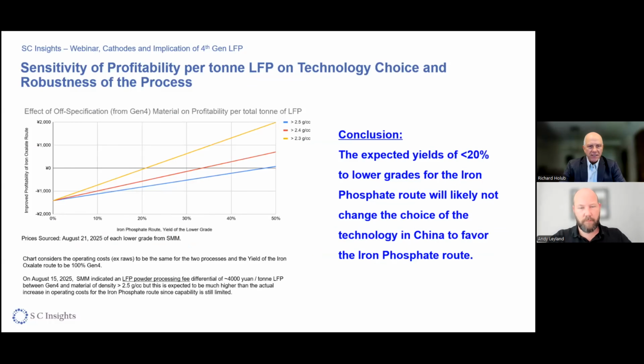So this is a simple sensitivity study on what I just mentioned, the yield to lower grade on the iron phosphate route. Across the x-axis is how much of the lower grade you would be making by iron phosphate, compared to the iron oxalate route at 100% yield on the y-axis. So the 1400 RMB per ton disadvantage is shown there on the y-axis intercept. As you go to the right, for the three different grades that you can purchase in China from the index prices, you see that you can make up to 20% of the lowest grade, or even up to 50% of the 2.5 grams per cc grade, and still just reach the break even. The choice of technology would be equivalent in both cases. So that's just a simple sensitivity study about how to look at the potential robustness problems of the iron phosphate route.